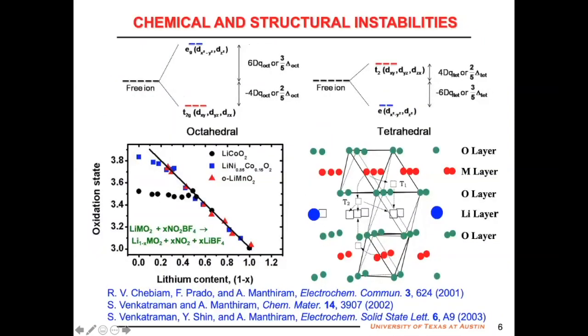For example, my group used to do a lot of chemical delithiation 20 years back. So if you keep on removing lithium from lithium cobalt oxide, the oxidation state does not increase below 0.5 lithium because you are not oxidizing cobalt anymore, you are losing oxygen. In contrast, you can go all the way to 4+ with manganese and nickel.